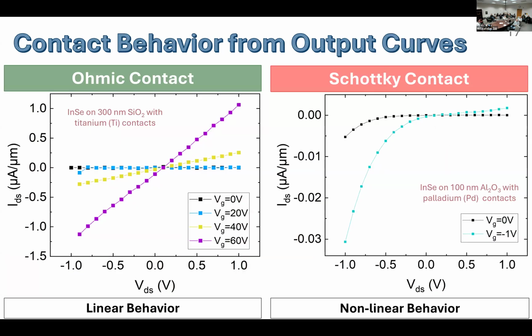So for our first measurements, or output measurements, we can actually get contact information from the type of behavior that they exhibit. If they exhibit a linear behavior, we can call it an ohmic contact. If they display a nonlinear, almost exponential behavior, we call that a Schottky contact. We can approximate whether or not they would be ohmic or Schottky, depending on the difference between the work function of the metal chosen and the Fermi level of the material that we're looking at.